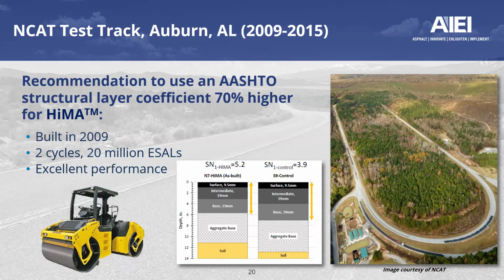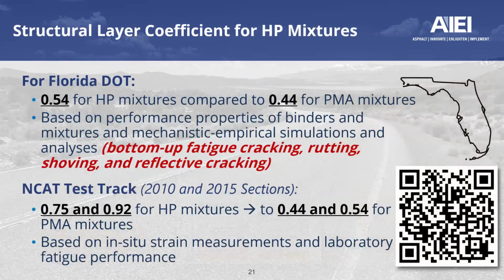If we take a look at the pavement structure here, we see that a 7-inch structure was equivalent to about 5 3/4 inches of HP mixtures. This did not stop here. Other state DOTs expressed interest in computing structural layer coefficients and doing a structural assessment for their pavement when HP technology is used.